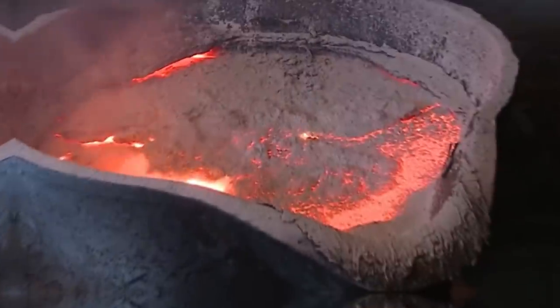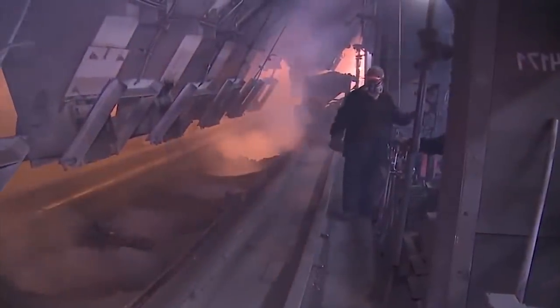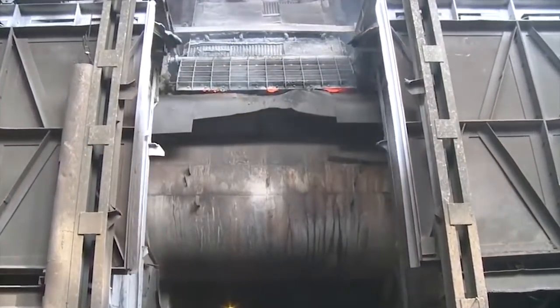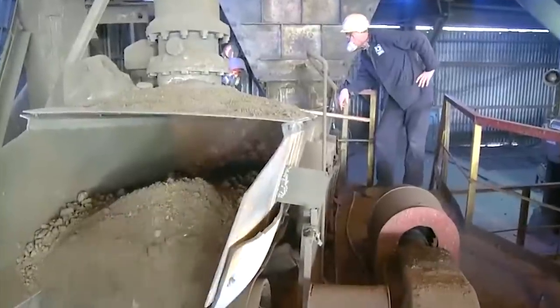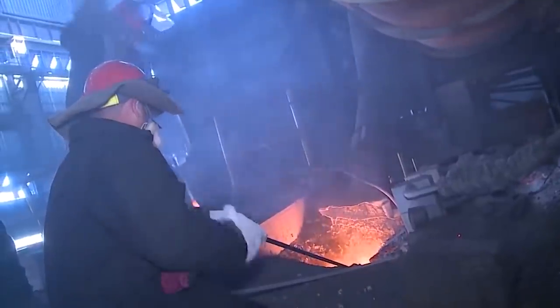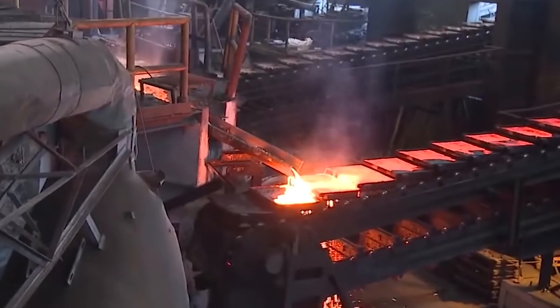The filtered liquid concentrate is sent through a 17-mile-long pipe to a smelting plant, where it is dried and then combined with oxygen in an oven to oxidize the iron and sulfur. The oxidized iron is separated, and the gaseous sulfur dioxide is isolated and sent to a local acid plant to be processed into valuable sulfuric acid. All that's left is the liquid copper sulfide, a so-called matte. The matte with 70% copper is cooled in water to form a hard compound similar to sand, then combined with oxygen in an instant-conversion oven that produces liquid copper with 98.6% purity.